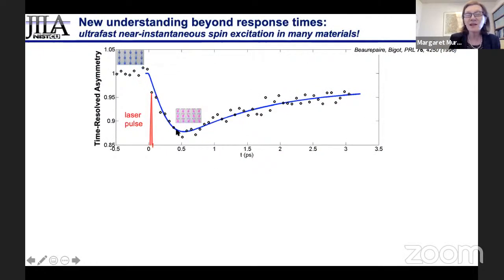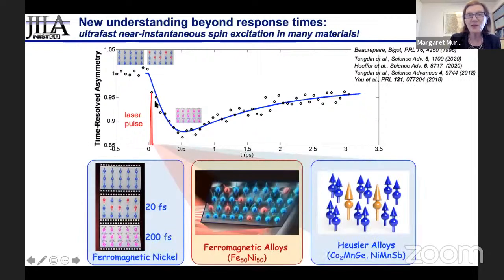instead of this interpretation of taking half a picosecond or so for the angular momentum to be dissipated by the lattice, what our measurements show is that there are these super excited states that correspond to high energy spin flips that happen during the laser pulse, where all the energy needed to drive the material through a magnetic phase transition is absorbed. And those high energy magnons then decay to lower energy magnons. And this is what a magneto-optic spectroscopy probes.